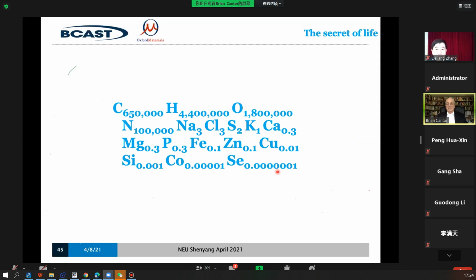We don't fully understand quite why. We need those 10 atoms of cobalt. We need those 100 or so, or 200 atoms in a trillion of silicon. This composition is very precise. If any of these slightly deviate and slightly change, I'm afraid human life is not possible and you die.